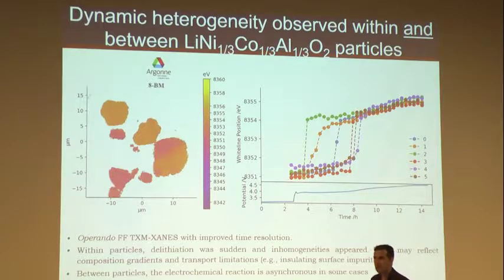And this probably reflects the balance of how much electrolyte you have in that area of your electrode, how much carbon you had in there, how well the electrode was made. It's probably a lot to do with the way that the architecture was put together. But this is a measurement that we've repeated multiple times, and we always see the same behavior on that first charge. We think what happens here is that the surface of these particles tend to form layers in contact with air that are insulating.